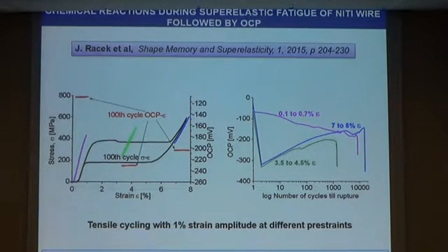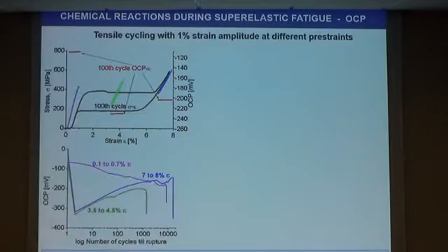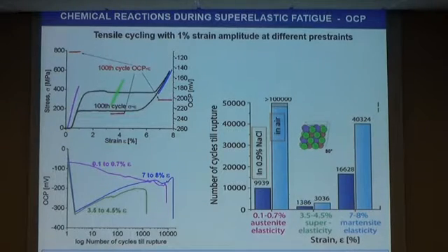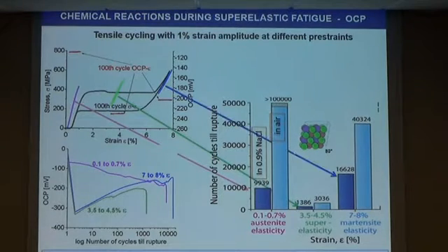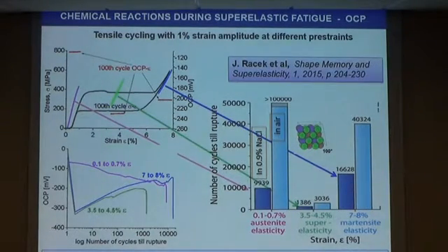This is somehow related to the pre-strain effect. Before, I spoke about full superelastic cycles, but now I will speak only about the elastic ones, elastic with small pre-strain. And this is in logarithmic scale. You see, by far the best performance is in the martensitic state. You have large stresses and large pre-strains, and see about 20 times higher number of cycles to failure under these conditions. So why is that? Maybe this is the summary. This is the performance in air, this is in fluid. Always in fluid it is worse than in air. But what should be compared here is the elastic regime, the transformation regime, and the martensitic regime. Here, by far, the largest.